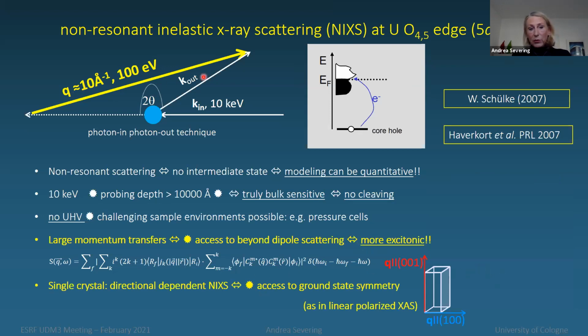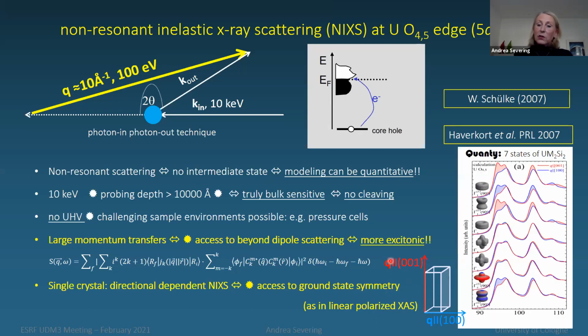If you now look at the momentum transfer relative to a certain crystallographic direction for a tetragonal material like the uranium MT2Si2 compounds, of course, we pick the 001 and the 100 in the plane, we can get access to the ground state symmetry like in a linear polarized X-ray absorption experiment. We simply exchange the direction of the electric field vector in X-ray absorption by the direction of the momentum transfer. And this here is a quantitative simulation of the seven crystal field states of uranium MT2Si2. And you see the seven states actually have very distinct polarization dependencies.